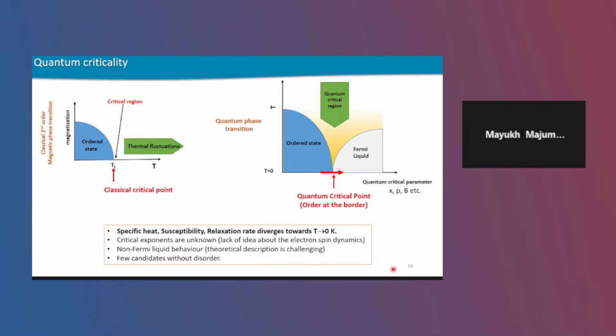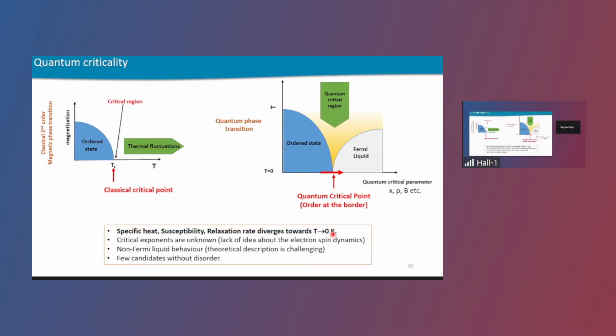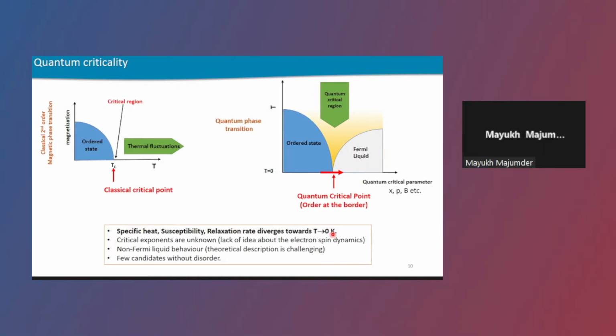And as a result, in case of quantum critical points also, you would expect that all the physical parameters would be diverging towards t equal to 0. But still, as I just mentioned, because of the effect of further temporal correlation length divergences, the critical exponents are rather less explored, or not that well known compared to the classical magnetic phase transitions. So this is the reason for which people have been discussing quantum criticality for quite a while.